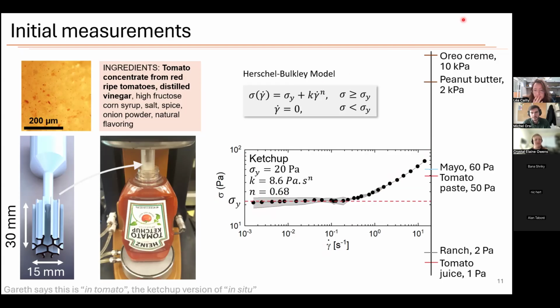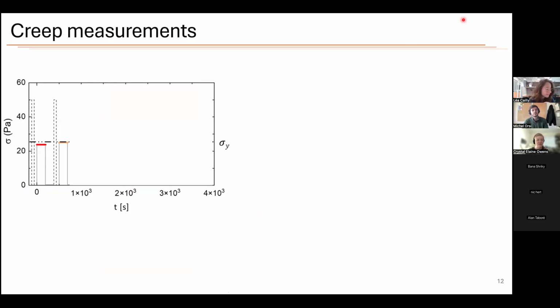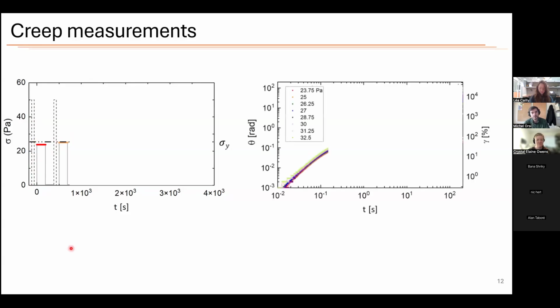So now we want to understand the time-dependent properties. What happens if you start from rest? To do this, we do creep experiments. How these work is you start with a pre-shear, a preconditioning step to reset the material to the same initial starting position for each of the tests that you do. And then you apply a constant stress, and this is the creep experiment. And we do this for different stresses relative to the level of the yield stress.